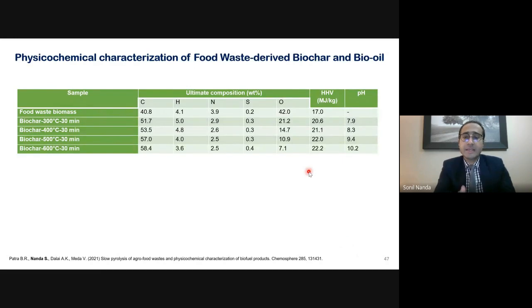Now, here is a CHNS, or the ultimate analysis of the food waste derived biochar and bio-oil. This table shows the CHNS analysis of biochar, which shows the composition of carbon, hydrogen, nitrogen, sulfur, and oxygen. These are the organic elements which are present in the biochar and bio-oil or any solid material. Here, you can see that the food waste biochar has a carbon content of around 41 weight%, but the carbon content tends to increase, up to 58 weight% when the biochar was obtained at 600 degrees Celsius. On the other hand, the hydrogen yield tends to decrease with the increase in the temperature and severity of pyrolysis, as does the nitrogen content, whereas the oxygen content also decreased.